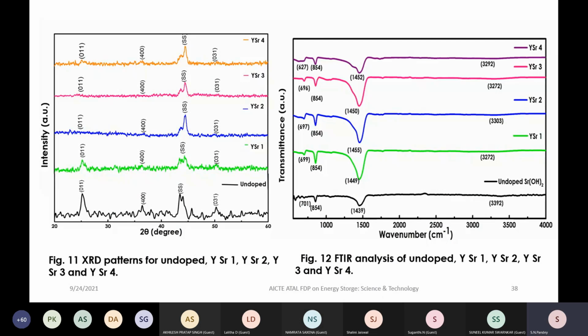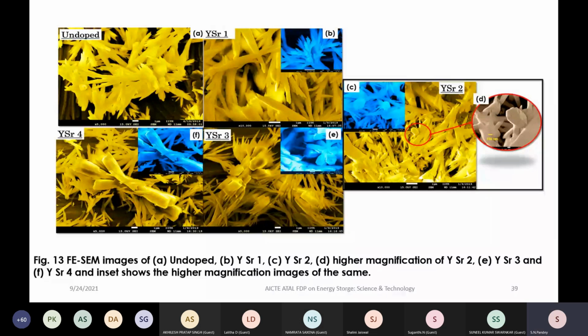And come to this FESEM. In the FESEM, one can see what is happening here. In the previous case, in the case of the tube, this is pure strontium hydroxide, we are having the tube rod structure. But it is very interesting to see that in three dimensions, something more is popping up due to the doping of the yttrium.